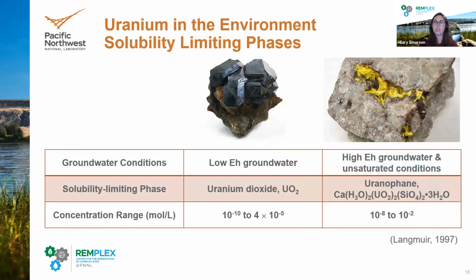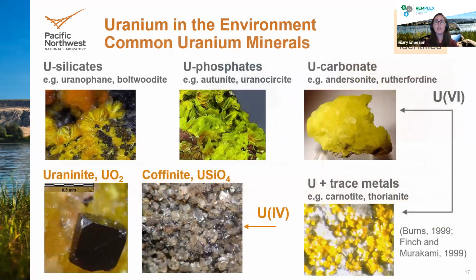And so I wanted to use this to transition to talk about some of the solid phases that we often see in the environment. And so again, when we have reducing conditions, we often see uranium dioxide or uraninite, with lower concentrations in the groundwater because of the lower solubility. And then under oxidizing conditions in groundwater and also unsaturated vadose zone conditions, we can see higher concentrations of uranium under different conditions, but with uranophane being one of the more common phases. However, it's not that simple.